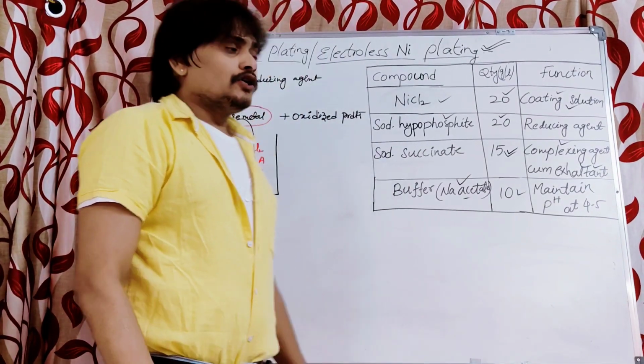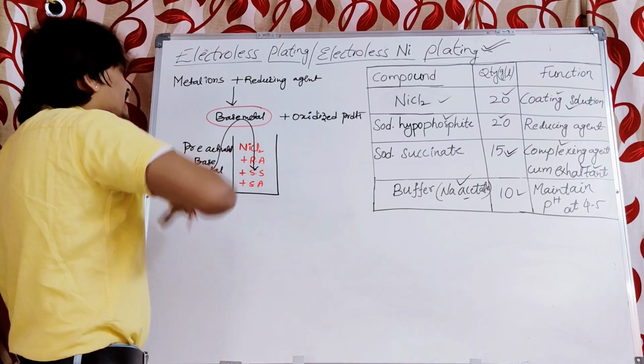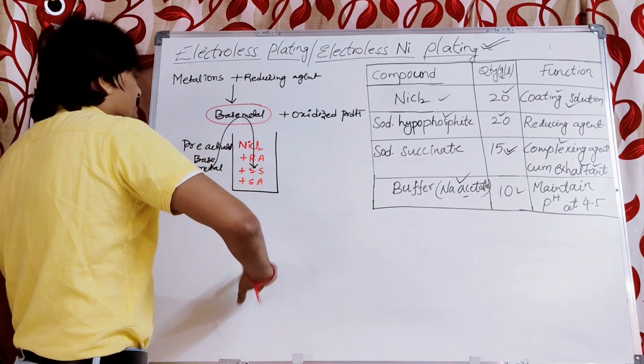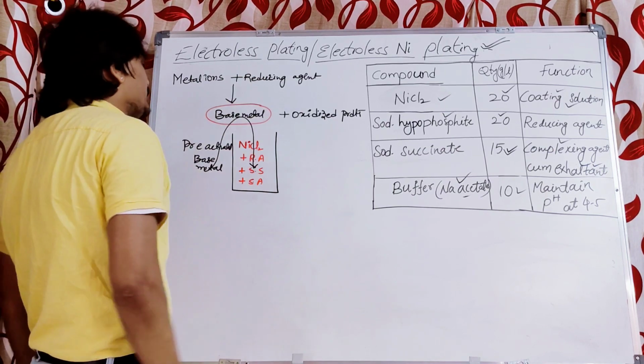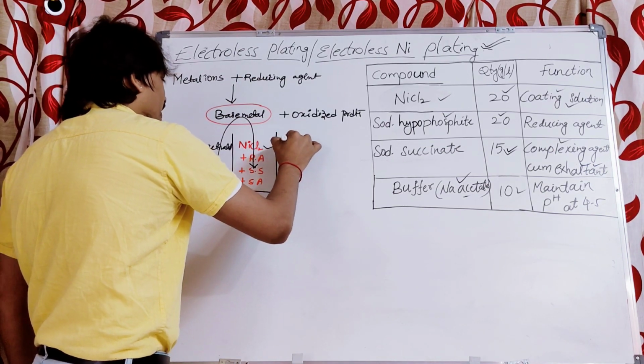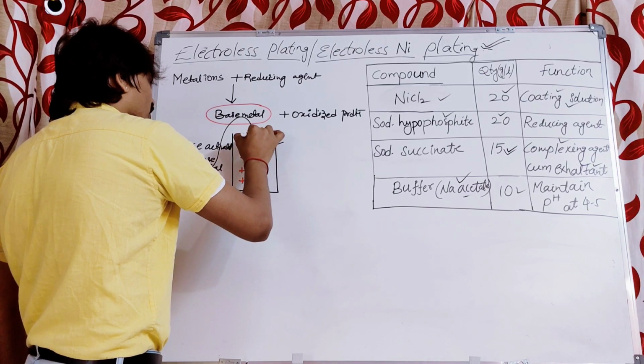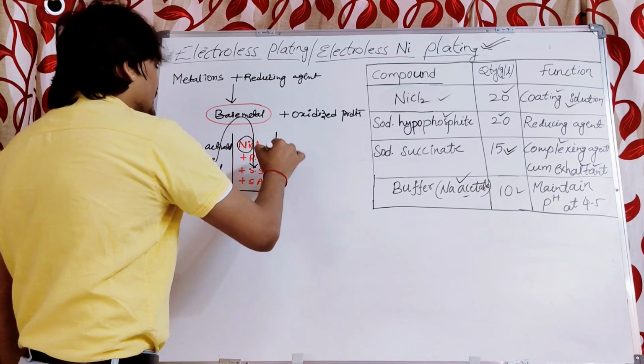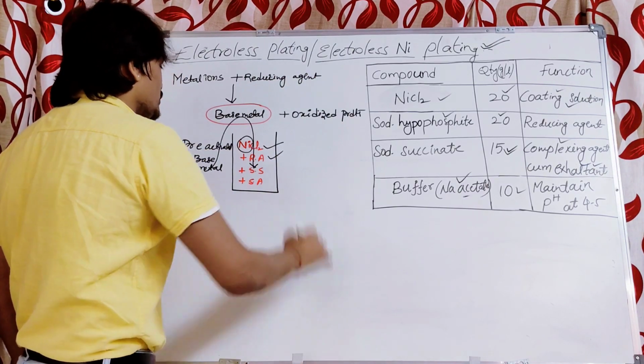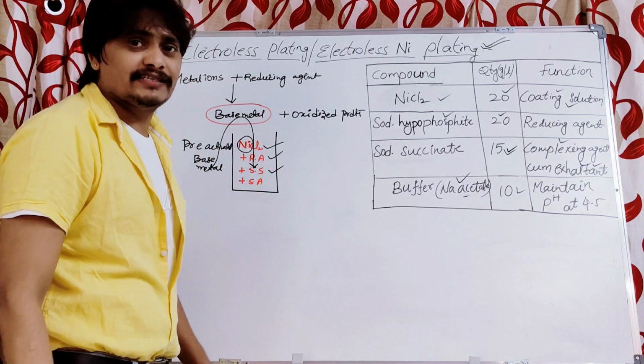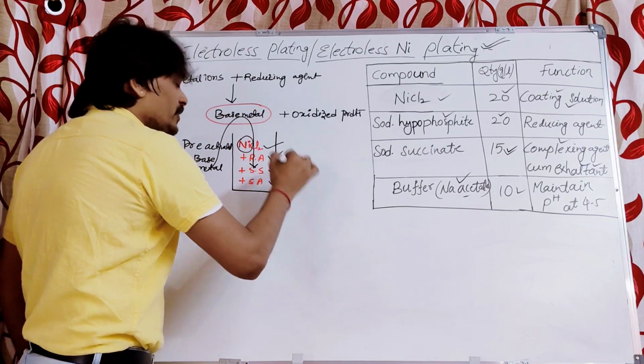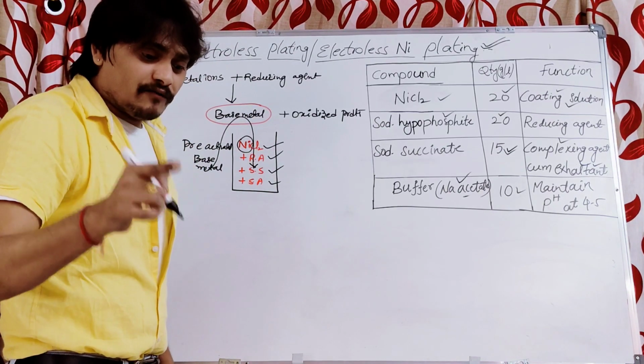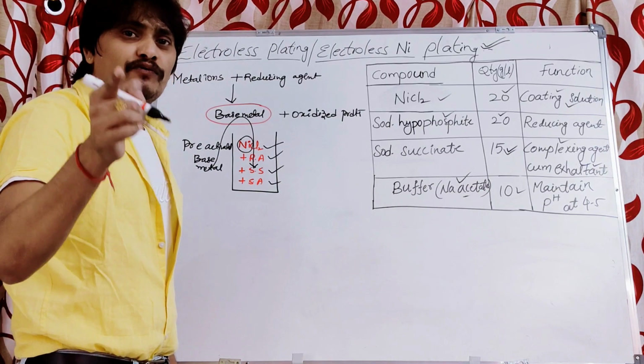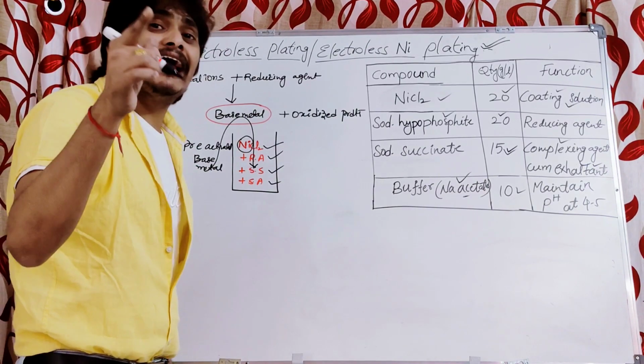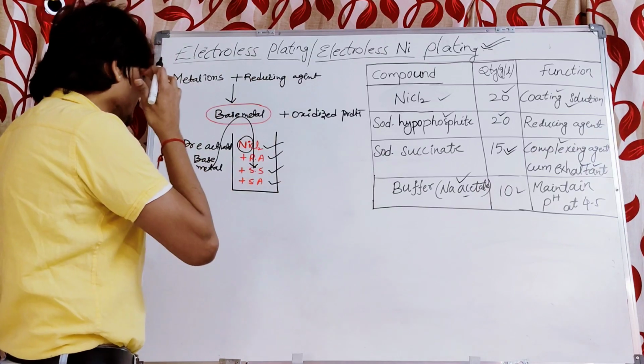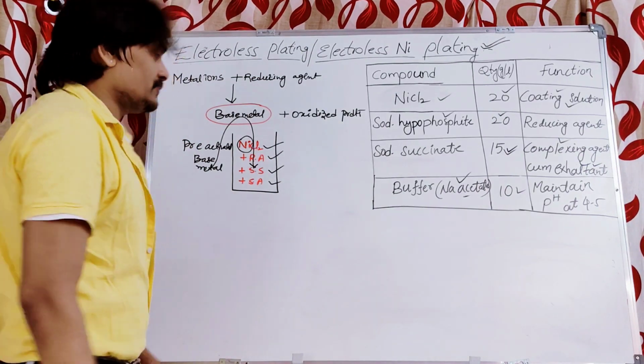Right. So now, whenever the pre-activated base metal is immersed into the composition comprised of the nickel chloride, which in turn comprises the noble metal ions, Ni+2 ions, and the reducing agent sodium hypophosphite, the sodium succinate, which is a complexing agent as well as the exaltant, and sodium acetate, which is the one maintaining the pH 4.5 in order to facilitate the reaction between the coating solution and the reducing agent, the following reactions take place.